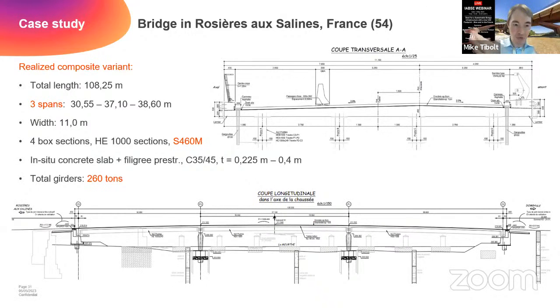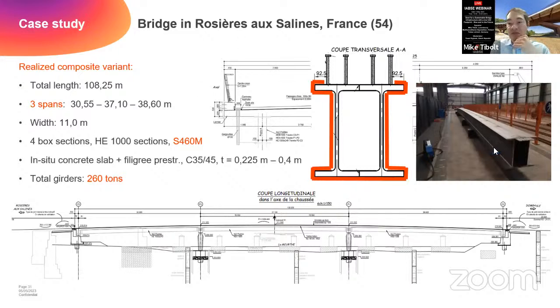So the total length remained, of course, untouched. But the composite solution was a solution where we put 2 hot rolled sections welded together on the upper and lower flange to form a box section out of hot rolled sections, as you can see here on this picture. And this can be realized in the workshop. And then by doing so, we could also reduce the number of spans down to 3, with spans between 30 and 38 meters. And we had 4 box sections in HE 1000 profiles in steel grade S460. Again, the high-strength steel to reduce the section size.